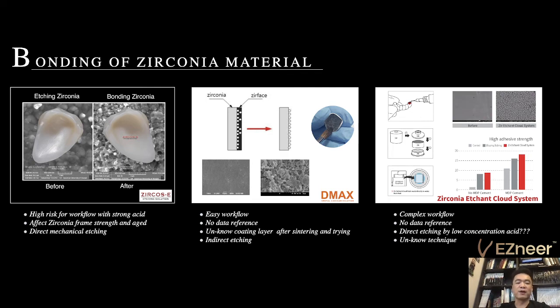And after the etching, the zirconia frame may decrease in strength and also affect some zirconia properties. So this is not good. But this is direct mechanical etching, and you can get a very rough surface. But the risk is the effect on the strength, and the properties change a little.